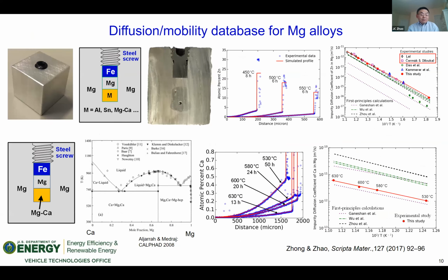And then, funded by the Department of Energy, we were asked to develop a mobility database, a diffusion database for magnesium alloys. So we came up with a very innovative way of making samples really fast. This is a piece of magnesium. We drill into it halfway through, and then we put in a piece of another metal like aluminum or a master alloy, and then we put a piece of magnesium on top, and then a piece of pure iron, and then we use a screw to tighten it up.